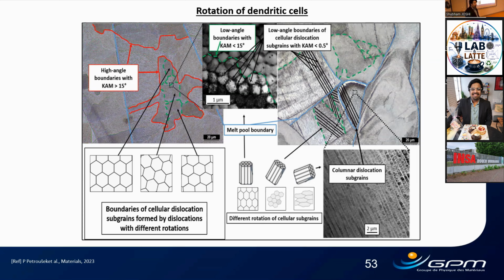Yes, yield stress. I'm saying it might have an influence. I'm saying the fracture and the crack initiation has no influence on yield stress, like the second aspect that I talked about. But these substructures may have impact on the yield stress as well. Also, anisotropy or not? Difficult to say. I think that on yield stress, the influence might be not negligible, but not as pronounced. But I feel they might have more influence when it comes to strain hardening, because when it comes to dislocation movement or probably fracture mechanics, they will play a significantly more important role.